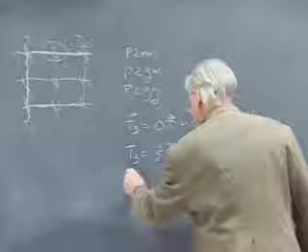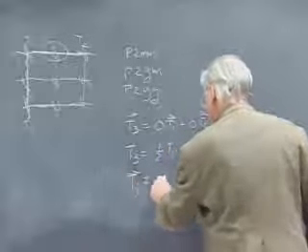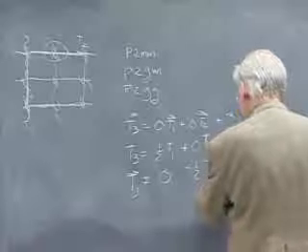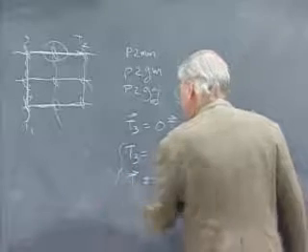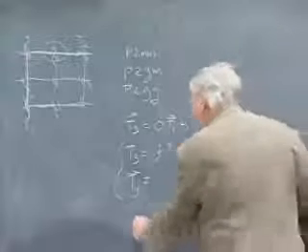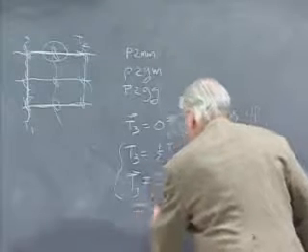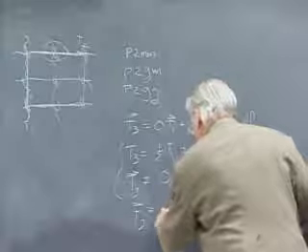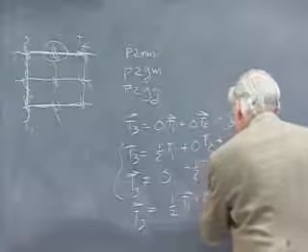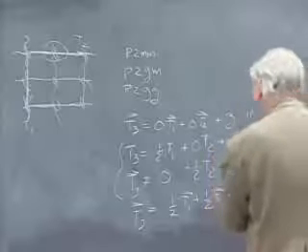Or T3 could be equal to 0 plus 1/2 of T2 plus Z. And they're both going to, upon redefinition, give the same result. Or T3 could be equal to 1/2 of T1 plus 1/2 of T2 plus Z straight up.